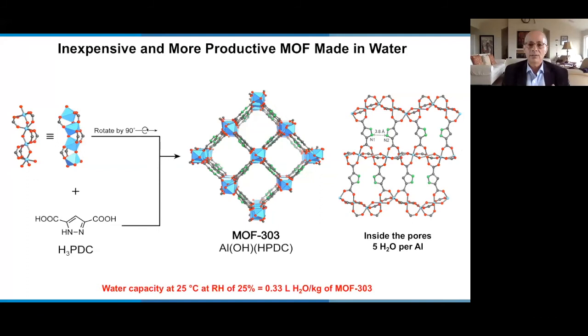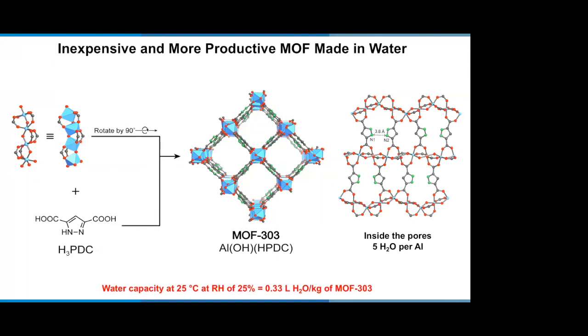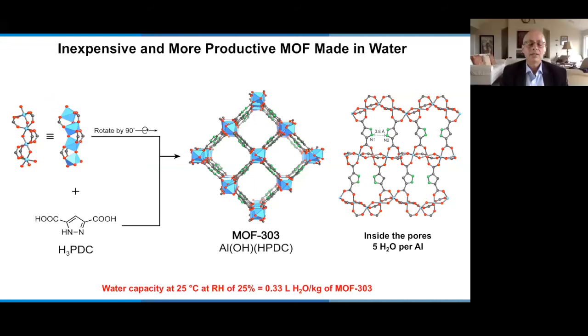Okay, so based on that, this is the nice thing about reticular chemistry: that structure was a zirconium MOF, and zirconium is expensive. So we want to make a structure based on aluminum because aluminum is cheap. So we chose these aluminum rods and linked them with this organic linker to make this structure. I won't describe it, but it's based on rods of aluminum oxide linked by organic linkers to make one-dimensional channels.